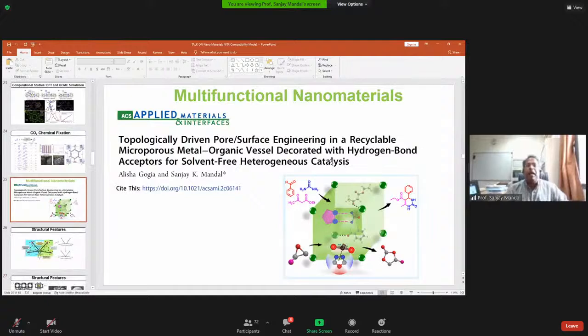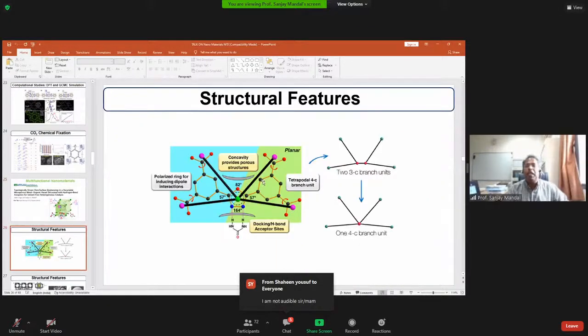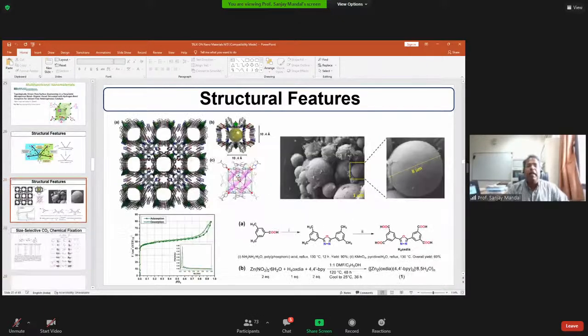The second paper is with a MOP, which was designed for heterogeneous catalysis, but for the sake of CO2, I'm going to tell you about this design, where you have the ligand, which is a carboxylate with an NN bond, and we have hydrogen bonding and that kind of thing. This is the crystal structure, which shows you have a 1 nanometer by 1 nanometer pore. If you look at the sphere from AFM, this is 8,000 nanometers in diameter. That means I have an 8 micron diameter, and that means I have 8,000 of those pores in this sphere.